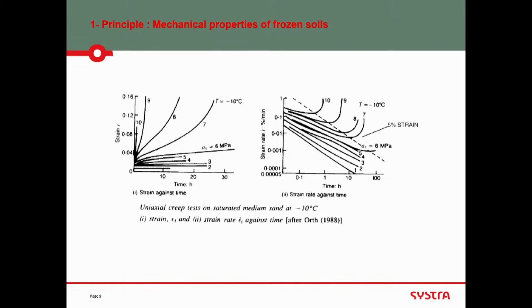But what is important is, can we, with creep, keep the strength under the critical strength so that there is no divergence? So if your structure of frozen body, frozen soil, is loaded for, let's say, 6 months, what we do is we compute what kind of stress can be applied so that after 6 months, the strength induced by creep does not reach a critical strength. Okay? So what has to be remembered is that it creeps a lot. In order to limit the creep, the acceleration of creep, in fact, we have to limit the stress. And we'll see what is a factor between a UCS, which is done on a very short term, and the long term that we are looking for, 3, 6, 8 months of excavation.